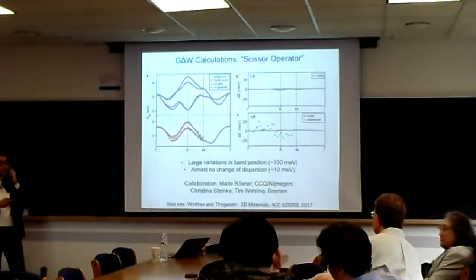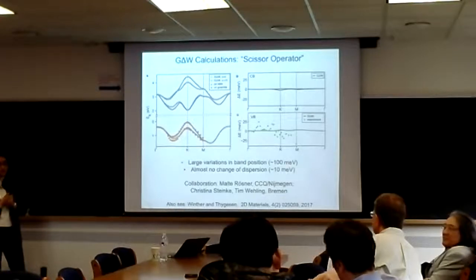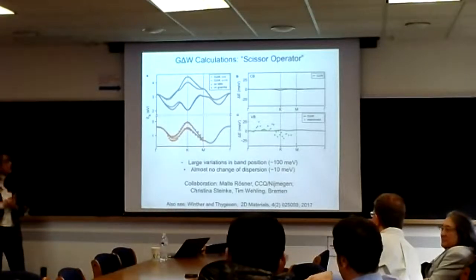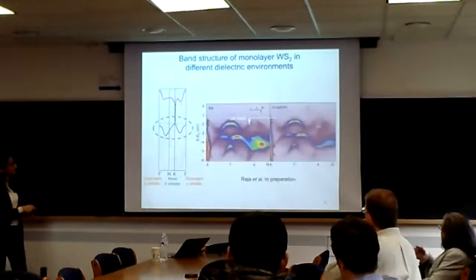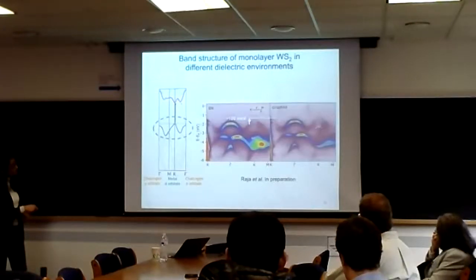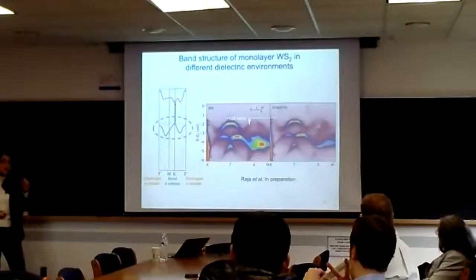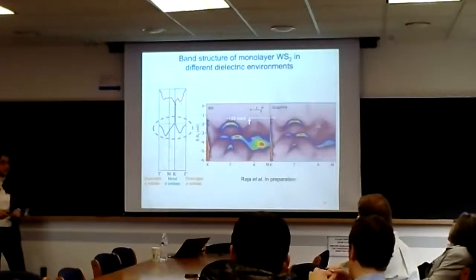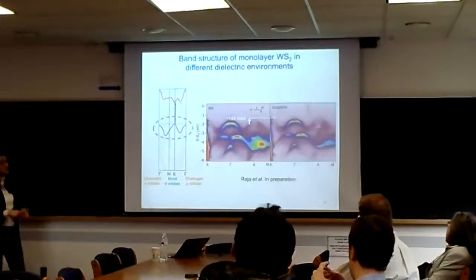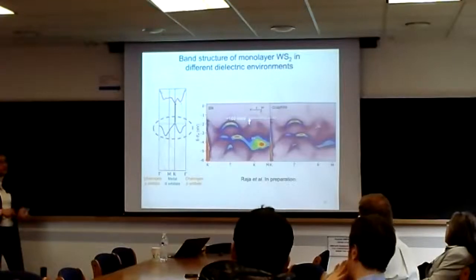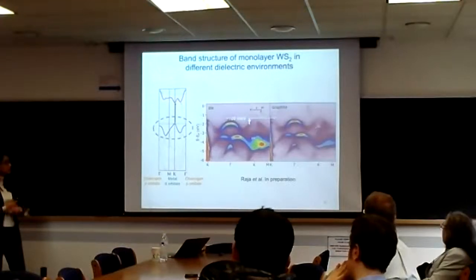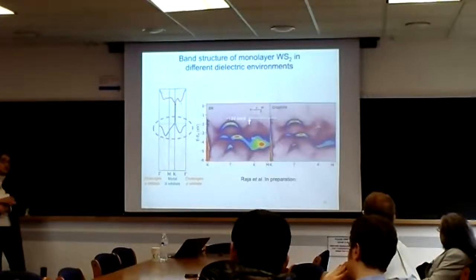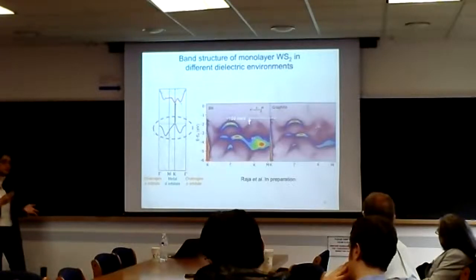But I suppose what I was trying to understand is that the photoelectrons only come from the dichalcogenide. They don't come from the layers beneath. Actually, you can see a little bit of intensity from the BN. It's only half a nanometer, so you definitely see shadow bands from underneath, but they're not hybridizing in any way. In fact, now people are suggesting putting a monolayer of BN on top of your sample and then doing the photoemission, which is even nicer because you lose some intensity, but you gain in sharpness of your line.